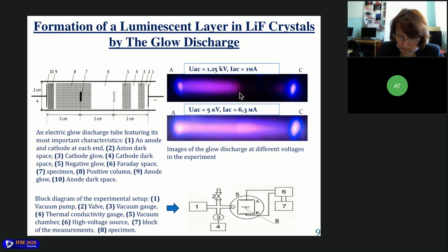Lithium fluoride crystals were placed in this region. One of them was placed in the positive column, you can see here. Then it was irradiated by a glow discharge. Then it was heated and we obtained the thermoluminescence curve. Another lithium fluoride crystal was placed here in the Faraday dark space, and we also obtained the thermoluminescence curve. So let's go to the next slide, slide number 10.